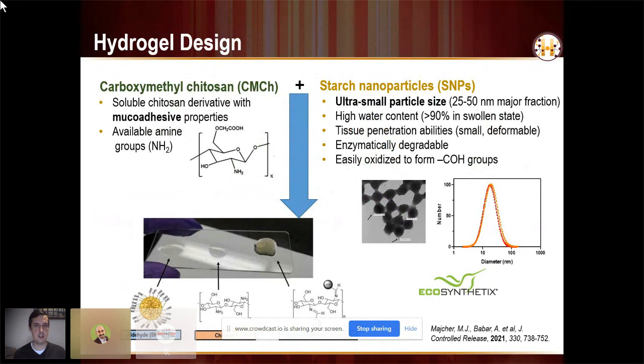One is carboxymethylchitosan, which is just a soluble derivative of chitosan, but a material that has these amine groups, which we can use for cross-linking and also have been found to be very beneficial for mucoadhesion. We combine those with starch nanoparticles. These are particles that were made by one of our research partners, EcoSynthetix, usually for paper coatings and wood laminate adhesives, not for biology. But it had extremely low particle sizes, and as a result, we found them to be extremely good at penetrating through tight junctions and getting through tissues that are hard to penetrate through, such as the nasal epithelium. They're also enzymatically degradable, clearable.